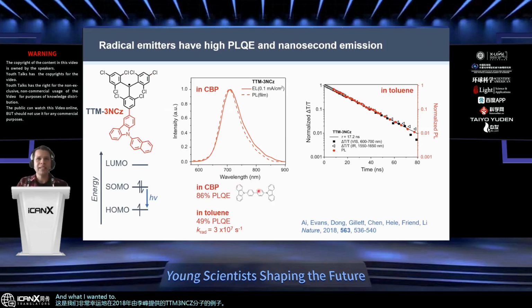And what I wanted to show you here is that this material is an excellent near-infrared emitter. It has a photoluminescence quantum yield of 86% in films, or 49% or so in solution. And what you can see here is that this efficient luminescence actually happens on tens of nanosecond timescales. So this is the time-resolved photoluminescence plot on the right-hand side.